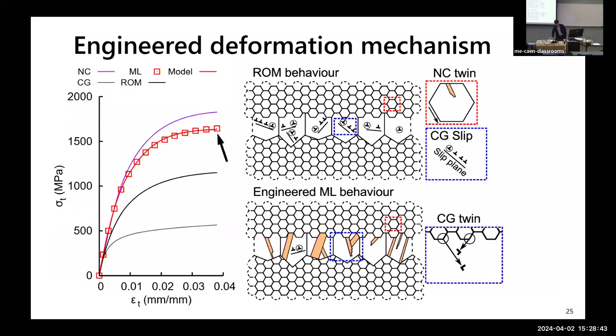What have we learned from this? That when you have very thick coarse grain layers, and you can think of this as a broader comment on the idea of heterogeneous microstructures, where you're not just having one very wide distribution of grain sizes, you're having two modulated grain sizes with their own grain size distributions, when the thickness of those layers is significantly larger than the crystal size, you do not see any crosstalk in the plasticity mechanisms. They're not significant enough to show up on a mechanical test.